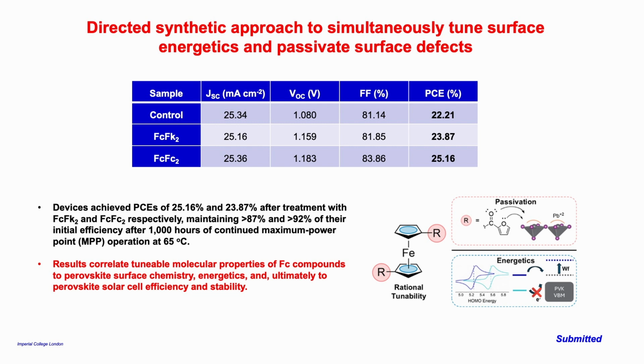The important thing as well, we've still got stability. So the substituents on the ferrocene are still what we call passivating that perovskite layer. They're preventing the defects happening over reasonable lengths of time, so 1,000 hours now. And at reasonable temperatures, we probably need to go a little bit higher, but we've got systems that we can tune to various applications.